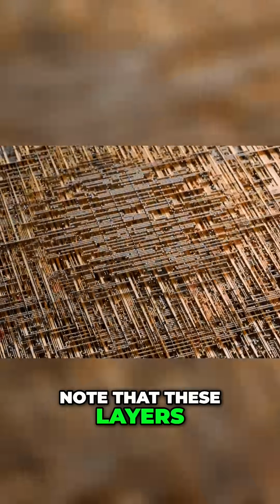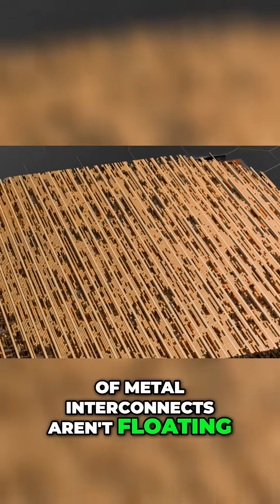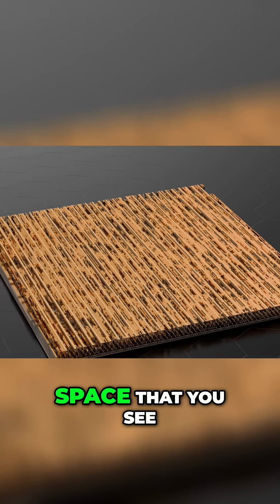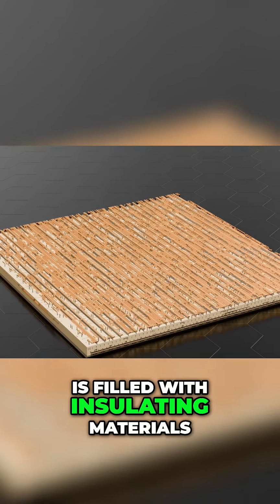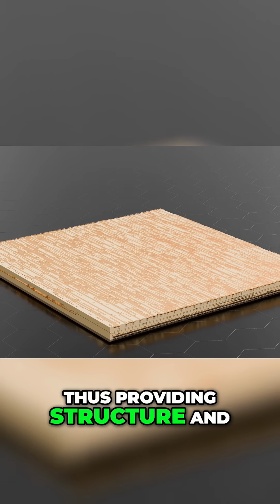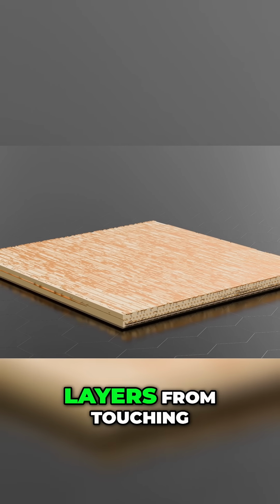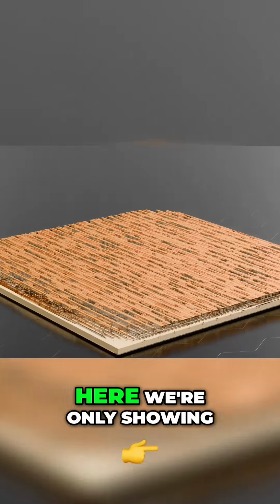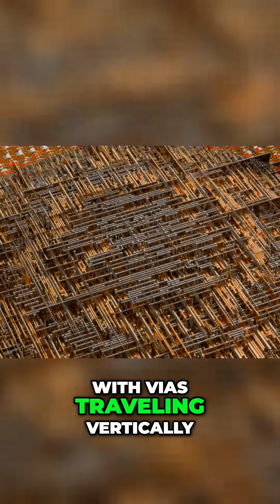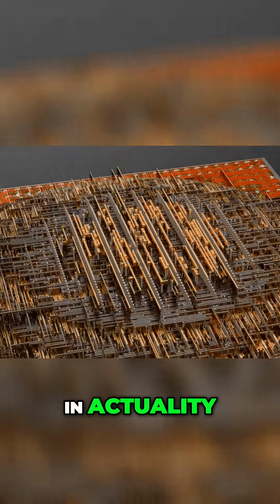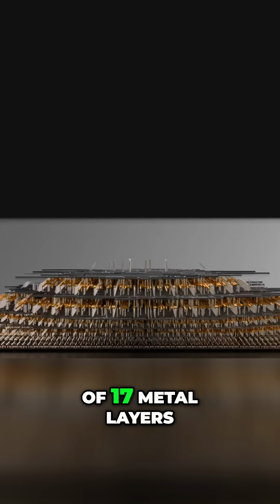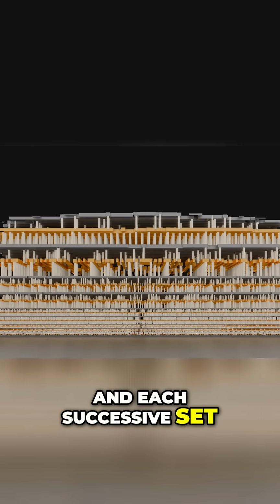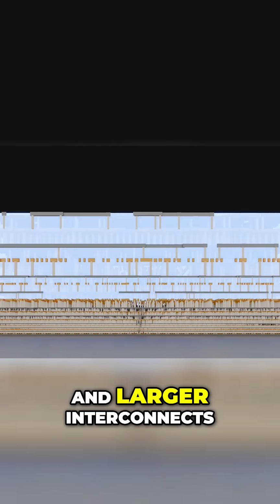Note that these layers of metal interconnects aren't floating, but rather the empty space that you see is filled with insulating materials, thus providing structure and preventing the metal wire layers from touching. Furthermore, here we're only showing the transistors at the bottom and 5 layers of metal interconnects, with vias traveling vertically between the layers. In actuality, there are a total of 17 metal layers of wires in the CPU, and each successive set of levels uses larger and larger interconnects.